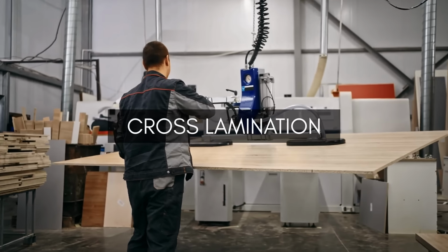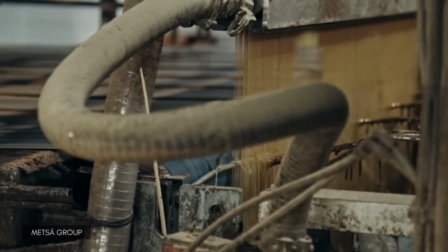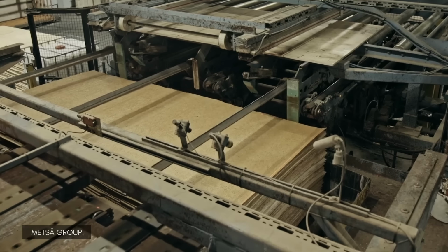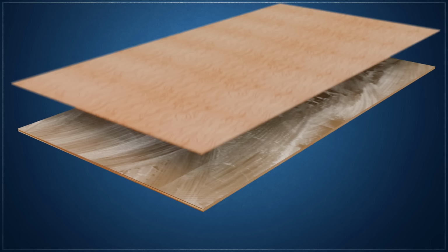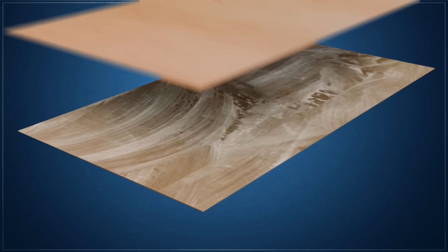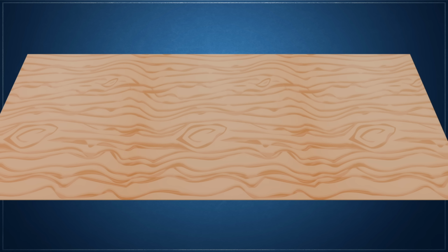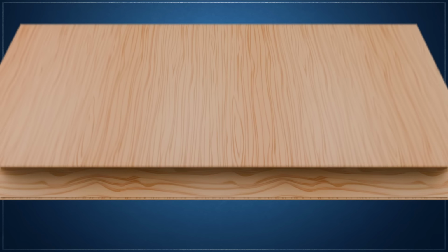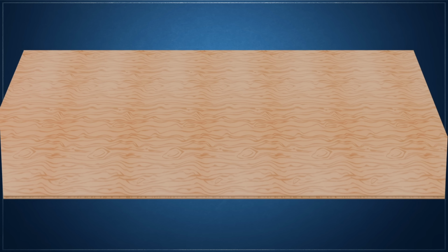In cross-lamination, wood is peeled radially into extremely thin veneers and glued together in a layup with an odd number of layers, where the grain of each alternating layer is typically rotated 90 degrees to the adjacent layer. This process, which forms modern plywood, eliminates the inherent weakness of one layer by counteracting it with longitudinal tensile strength of the adjacent perpendicular layer. The negligible longitudinal shrinkage of the cross-banded layers also physically restrains the high tangential shrinkage of the core layers, resulting in a panel that is dimensionally stable, warp-resistant, and quasi-isotropic.